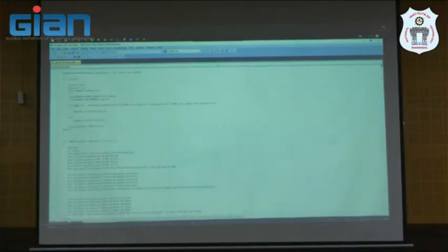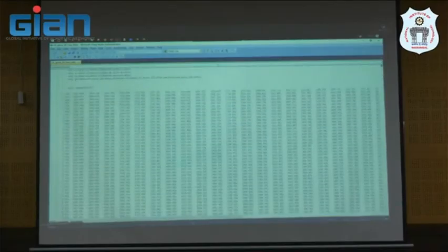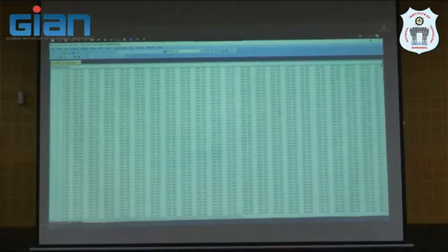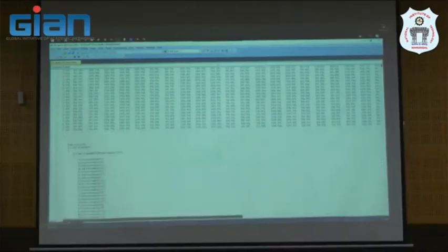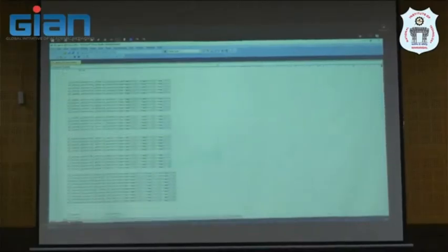This one. This is what? This is the cellular automata, right? This is a micro. Yes, cellular automata and the linear, and here is the temperature from the previous model. Temperature from the macro, and we will do some linear interpolation.